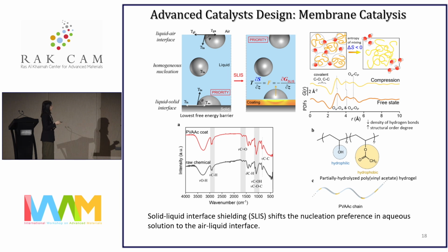So in this work, I would like to show you that in a typical aqueous system, due to the lowest free energy barrier, the nuclei formation is usually preferred at a liquid-solid interface over the homogeneous nucleation or over the liquid-air interface. So in this work, we have used a partially hydrolyzed polyvinyl acetate hydrogel, and its molecular structure is shown in the FTIR here. And we have the acetate group, which makes it hydrophobic, and then hydroxyl group, which makes it hydrophilic. And this gives it the ability to have insolubility as well as water swelling ability in the aqueous solution, respectively.